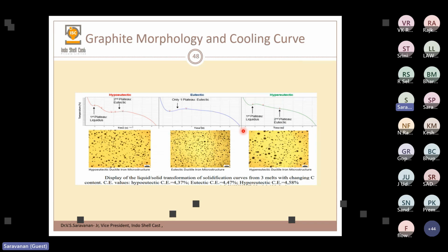Here, what I told, there is the length, how much it is traveling, and how flat it is. So that decides. The curve shows how much early graphite precipitates and how much late graphite precipitates. Early graphite precipitation is more in hypereutectic metal, and then you can see the graphite size a little bit more in the metal. Here also it is hypereutectic, early graphite precipitation. You can see the graphites are a little bit on the bigger side, and this is eutectic, meaning it is almost uniform graphite size. So like that, from the graphite also